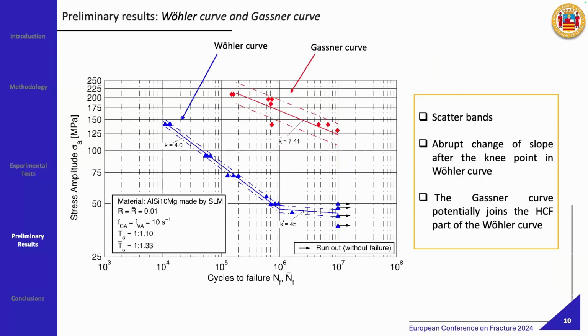And so I'm concluding, showing you our very preliminary results because the experimental campaign just started. So in blue, we have the results for the constant amplitude test, while in red, the results for the variable amplitude test. We can see how concerning the constant amplitude test, so the Wöhler curve, the scattering is very limited. So the width of the scatter band is very limited as well. We can see how there is an abrupt change in slope in the Wöhler curve in correspondence of the knee point, and this result is in accordance with the literature.